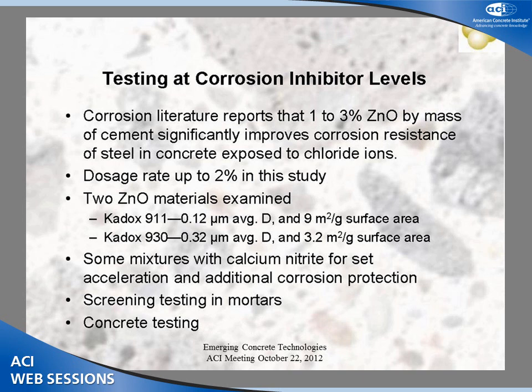So we're talking about very minute materials. Some of the mixtures that we looked at contained calcium nitrite, a tried and true corrosion inhibitor that's been used in the concrete industry for a number of years. The reason why the calcium nitrite was included in some of the mixtures is because not only is it a corrosion inhibitor, but calcium nitrite is a very effective accelerator. And it can potentially offer additional corrosion protection.